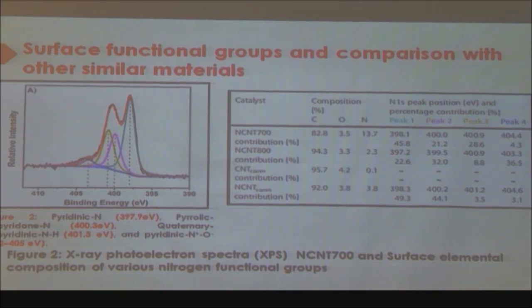So this really shows this in the tabular form. I don't want to go into the detail of that, but let me simplify it. From this analysis, we really make sure that nitrogen is there on my carbon material, right? And I make sure in which forms the nitrogen is present. Once we know this, we quantify how much carbon is there, how much oxygen is there, and how much nitrogen is there. So if you see NCNT 700, 700 is the temperature that we use for making this material. At 700 degrees centigrade, the nitrogen content is maximum.